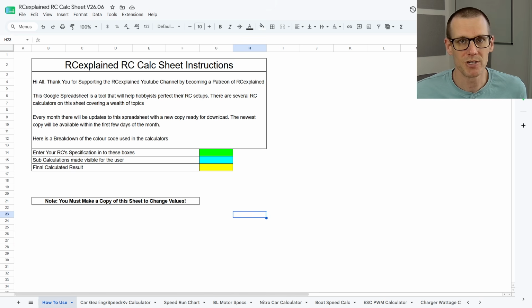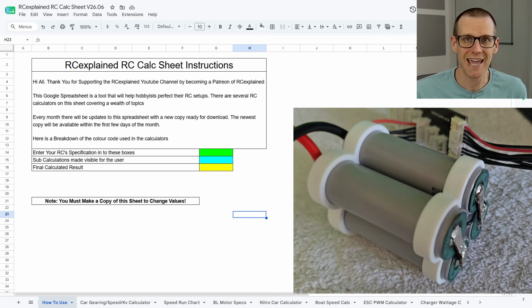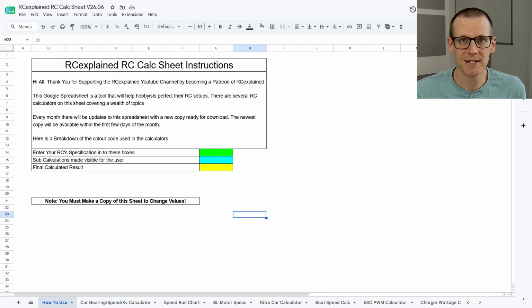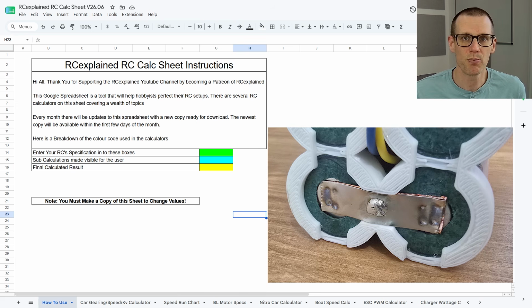Now, when it comes to the materials that we are using for these packs, when I am soldering the cells together, I am using a 1mm by 5mm copper bar. And when I am welding the pack together, I am using a 0.2 by 8mm piece of copper on the bottom layer, immediately touching the battery. And on top of that layer, so I can properly weld, I am using a pure nickel at 0.2mm as well. So in total, we got 0.4mm of material, where our copper is the bottom 0.2mm.